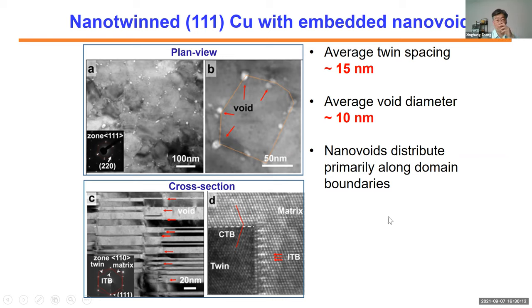So now we have introduced some nano twin and nano void networks. The question is, how do they evolve? You might think this is a bad idea because void swelling has been proven. Most people will be concerned about, well, you have voids already. This is what will grow and make it worse. I will have even larger voids after radiation.